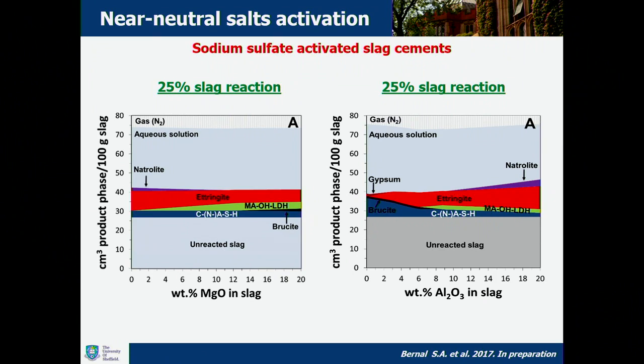We did some thermodynamic modeling of these systems to identify what's going on when we have different chemical compositions, and also why we see this precipitation of reaction products at different times of reaction. We can identify, for instance, that when we vary the magnesium content within the slag, there are no significant changes in the amount of C-A-S-H phases we form in the system. But what's really interesting is how at very low contents of magnesium, we favor formation of hydrotalcite.